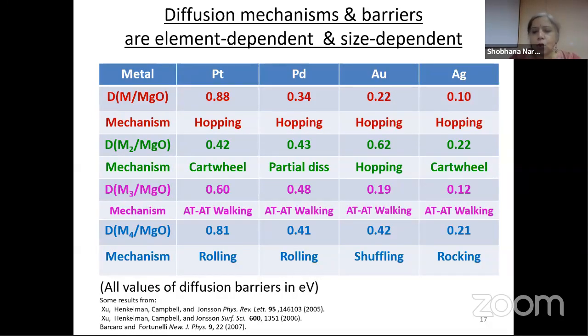Now, diffusion, the interesting thing, okay, there's a lot to see in this chart. I have listed two things in this chart. One is the mechanism by which the cluster moves along the surface, and the other is the diffusion barrier. I will discuss this more. But the important thing is that the mechanism by which the cluster moves is not always the same. It depends on the element. And also the barriers by which they diffuse are very element dependent. So what are these mechanisms?